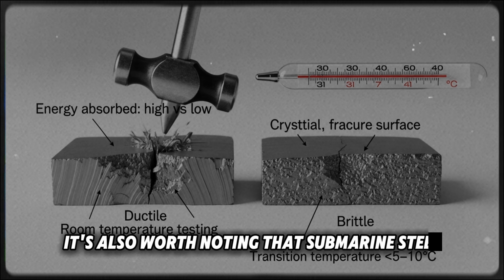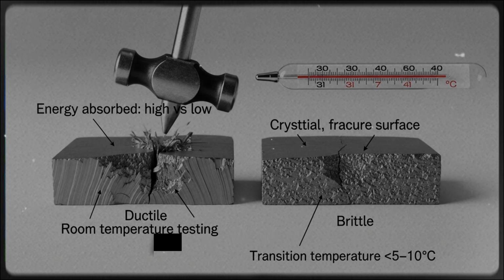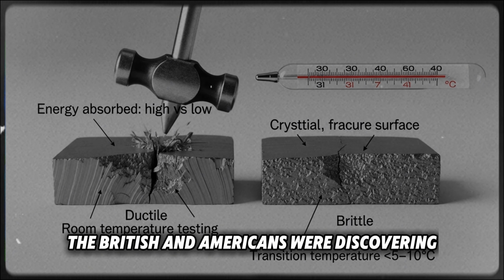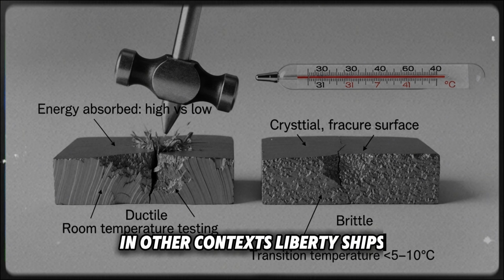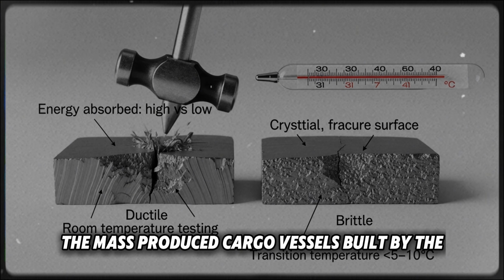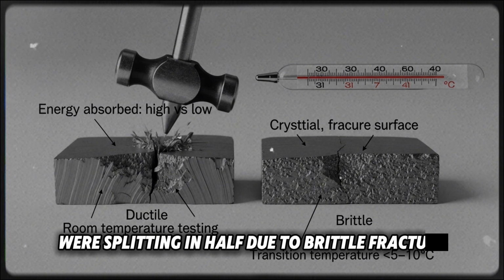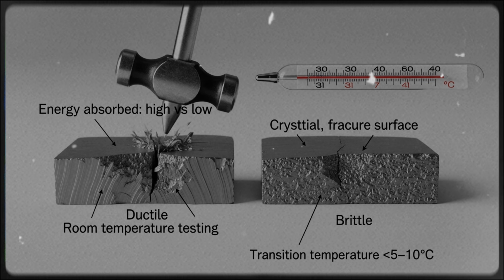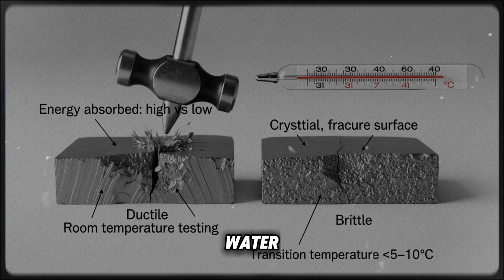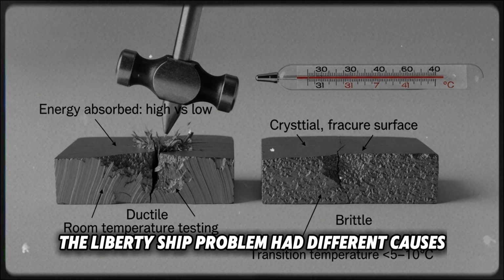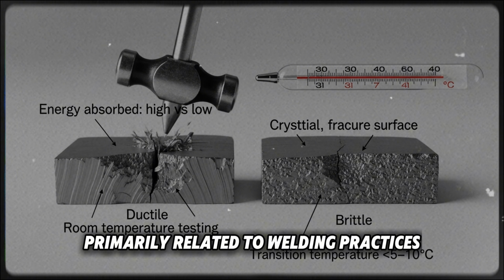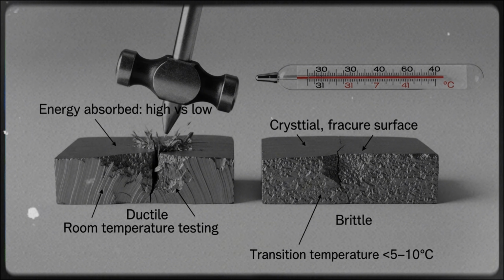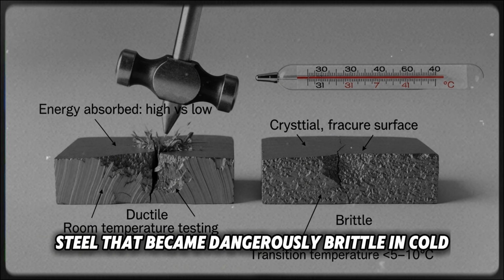It's also worth noting that submarine steel wasn't uniquely German in having this problem. The British and Americans were discovering similar issues in other contexts. Liberty ships, the mass-produced cargo vessels built by the United States, were splitting in half due to brittle fracture. The SS Schenectady famously broke completely in two while docked in January 1943. Many Liberty ships developed cracks in cold water. The Liberty ship problem had different causes, primarily related to welding practices and stress concentrations at square hatch corners. But the underlying material behavior was the same: steel that became dangerously brittle in cold water.